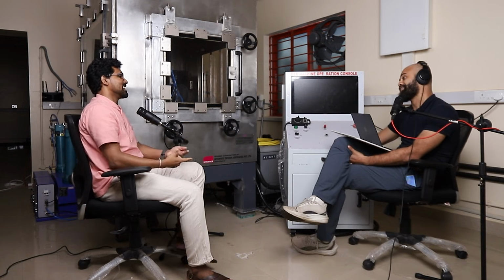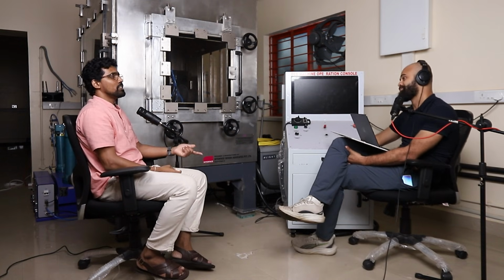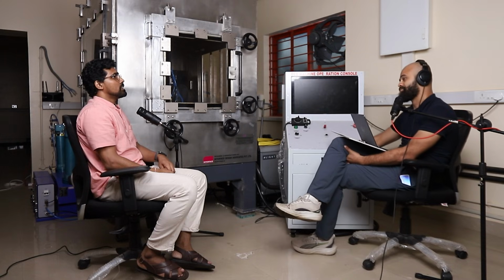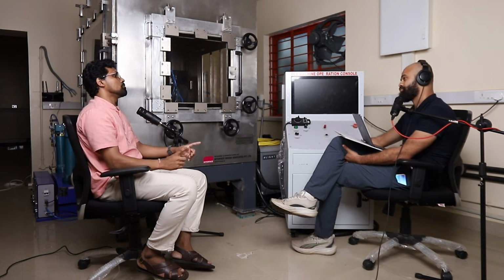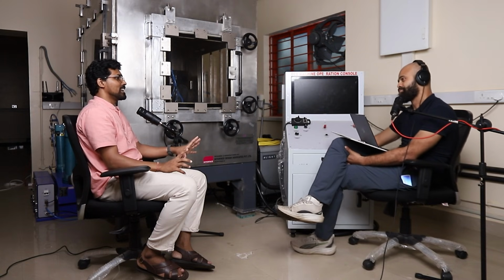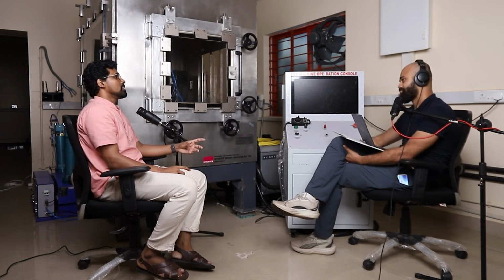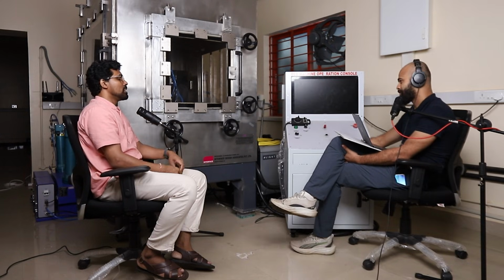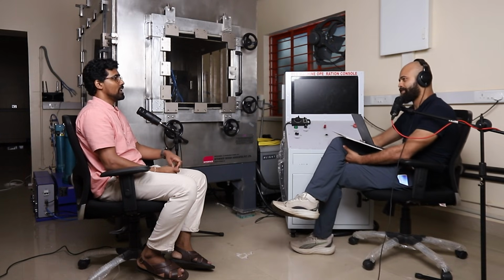Single crystal came later. The immediate thought they had was that if we can just make it one single crystal, just one single grain, then that would reduce the creep failure and would increase the life. Now, you cannot directly jump from a polycrystalline to a single crystal. So you need to understand how you can get larger grains instead of smaller grains. So you first reduce the number of grains.